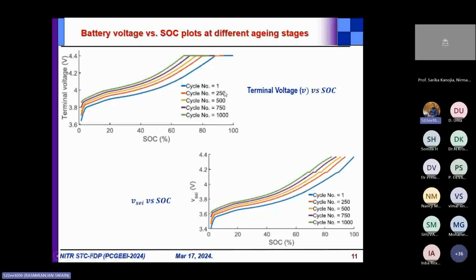Now when you see cycle number 250, that corresponding data, the red one, you see that it has shifted to the left side. Now if you go further to cycle number 500, this is all based on experiments. If you do an experiment on this, you will observe this kind of characteristics. Cycle number 500 has again shifted, cycle number 750 has again shifted. So gradually there is a sink along the y-axis, you can see. From this point to this point, this is the effect of aging.